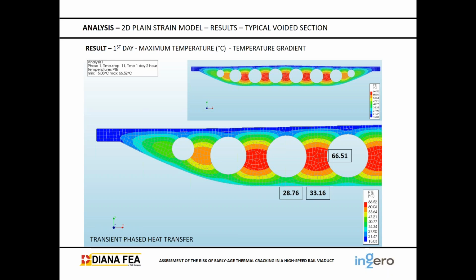It was a 2D plane strain model. And for the typical void section, from the first day, we get the maximum temperature of the process. And in this image, we can see that the temperature in the nucleus, in the core, was 66 degrees, and on the outer part, it was 33 degrees, okay? We can see the temperature gradient, which is induced by the heating of the concrete between the inner part and the outer part.